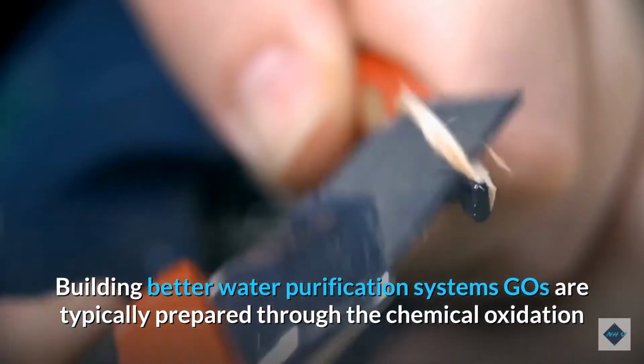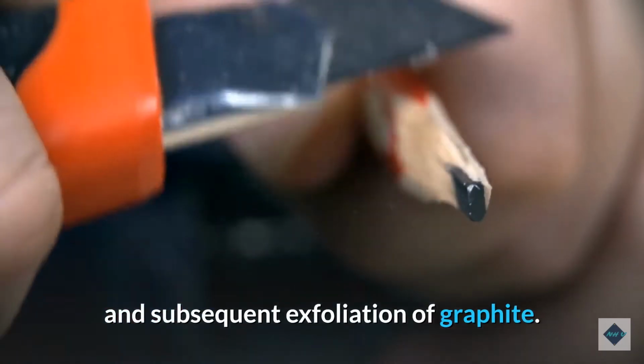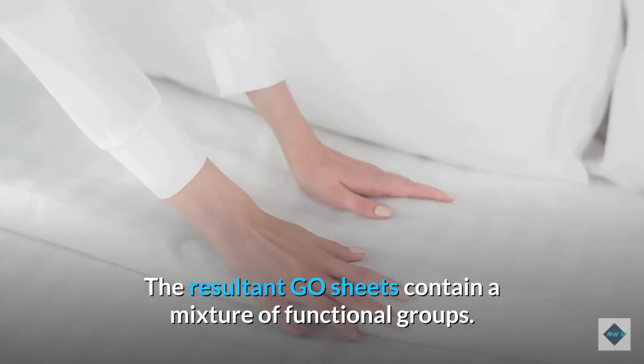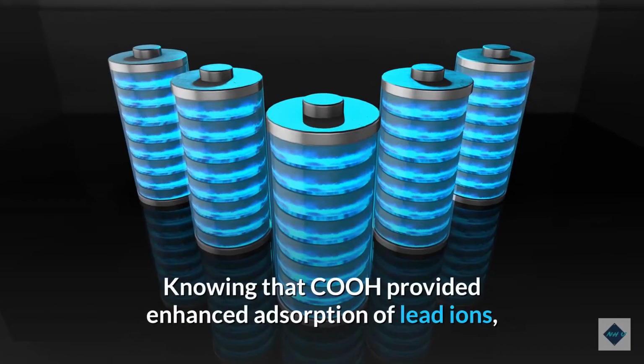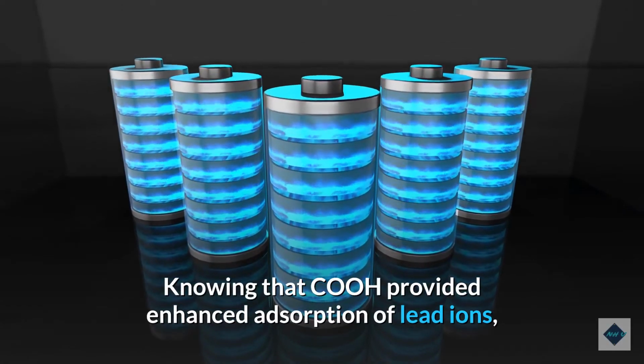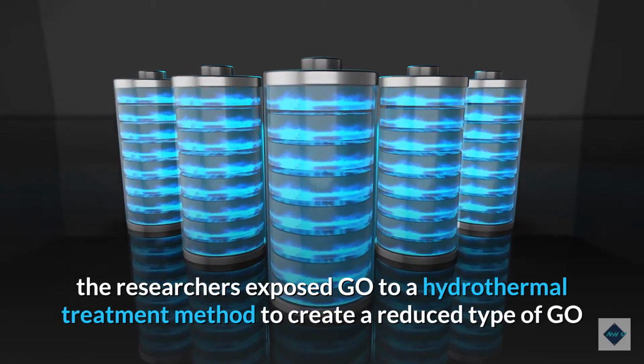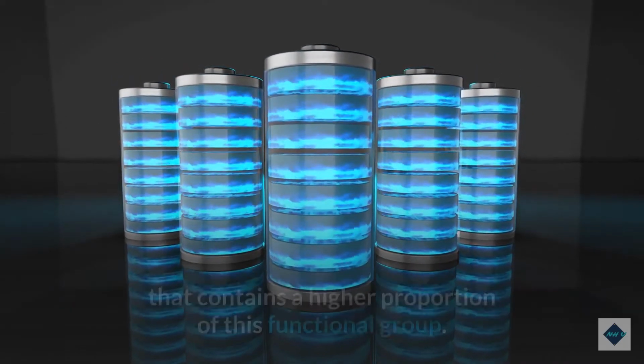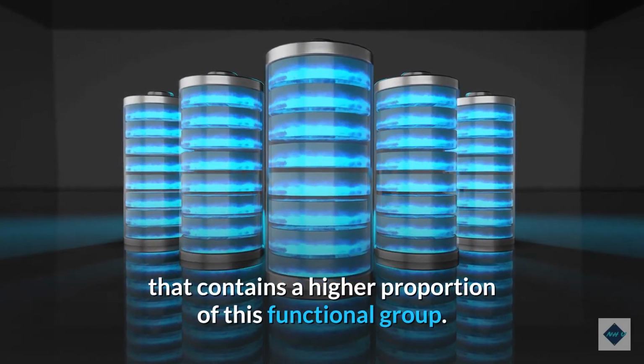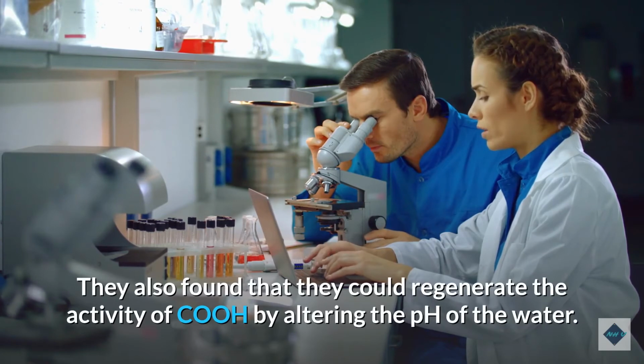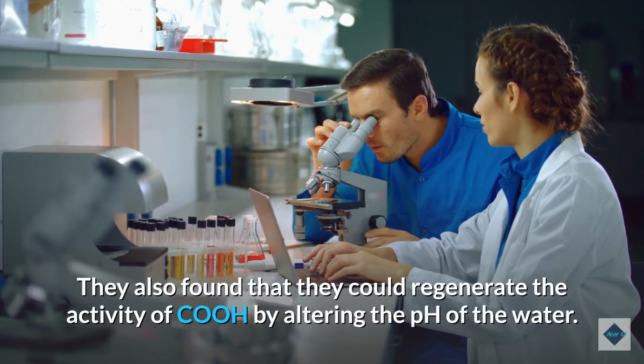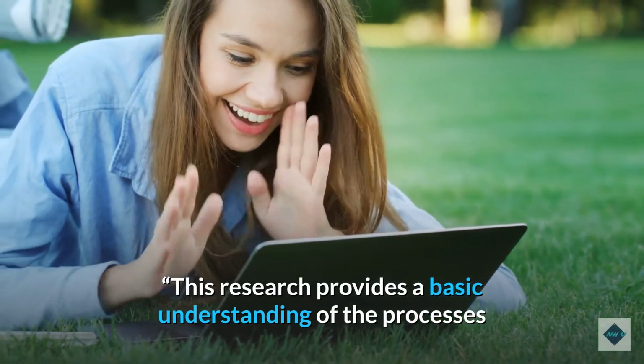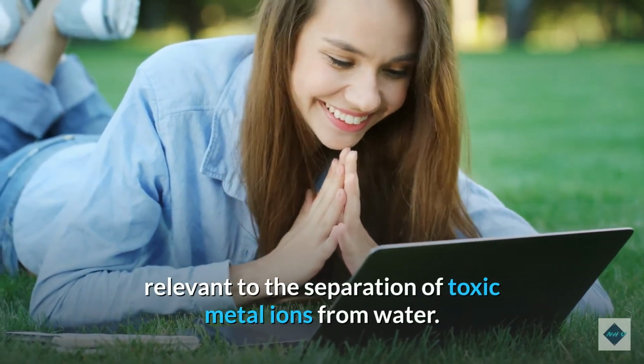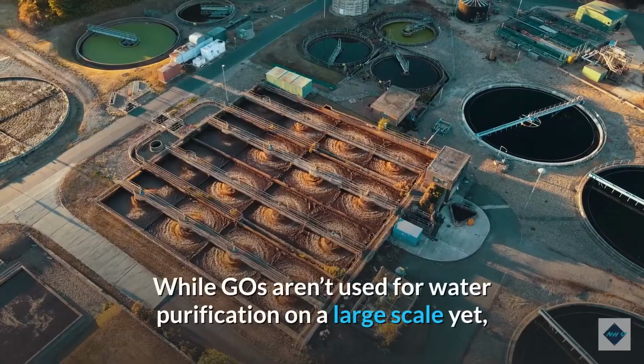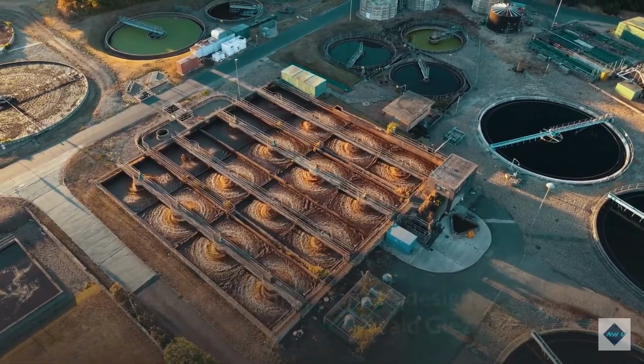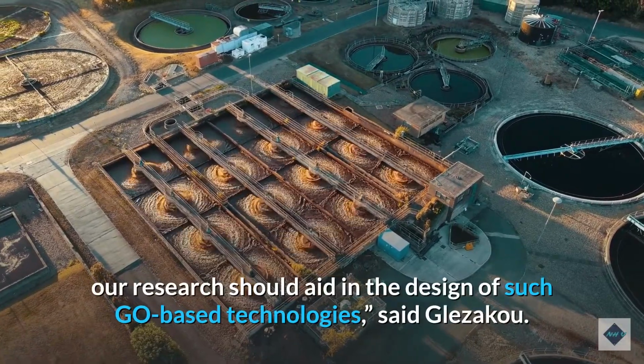Building better water purification systems. GOs are typically prepared through the chemical oxidation and subsequent exfoliation of graphite. The resultant GO sheets contain a mixture of functional groups. Knowing that COOH provided enhanced adsorption of lead ions, the researchers exposed GO to a hydrothermal treatment method to create a reduced type of GO that contains a higher proportion of this functional group. They also found that they could regenerate the activity of COOH by altering the pH of the water. This research provides a basic understanding of the processes relevant to the separation of toxic metal ions from water. "While GOs aren't used for water purification on a large scale yet, our research should aid in the design of such GO-based technologies," said Glezakou.